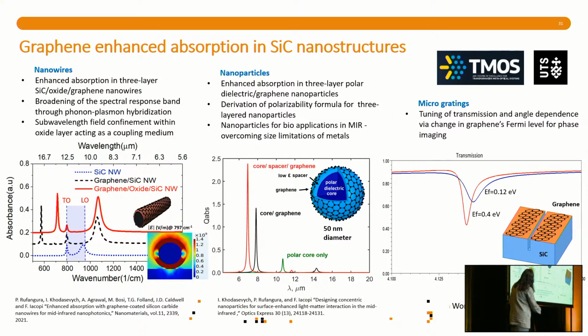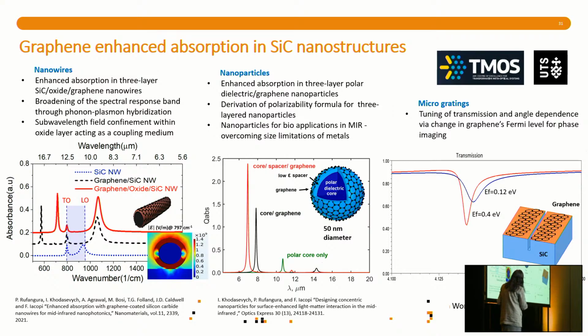And then we have already looked at quite a lot of different structures. So the beauty of the system is that it allows us to do a lot of different structures with no problems at all. We just have to pre-pattern the silicon carbide, and then the graphene will just coat around. So we worked with nanowires, as you saw before, and this is a very good example, actually. This curve here, the blue one, is the example where you have nanowires made of silicon carbide only, no graphene. And so you have the TO, that's always there. And then you have the phonon here within the Reststrahlen band, but you can see that the absorption is really small, and also is restricted in that band, as I said before.